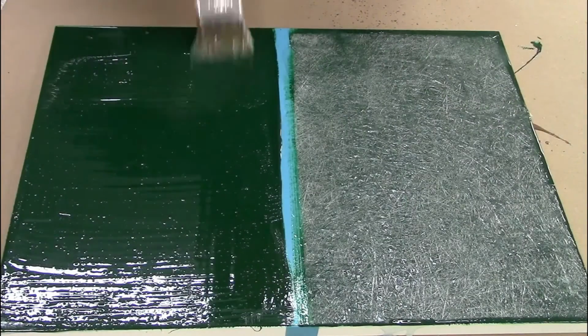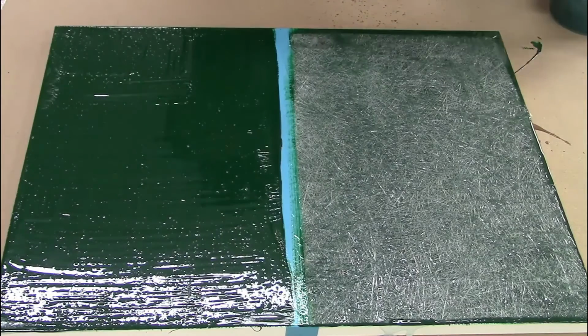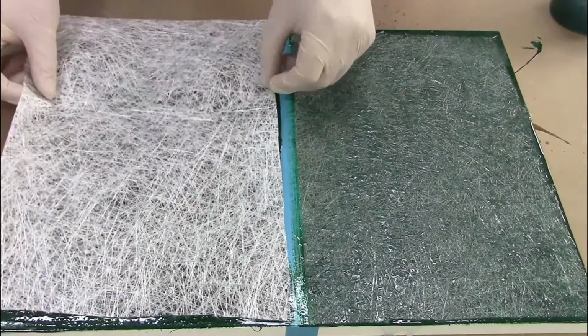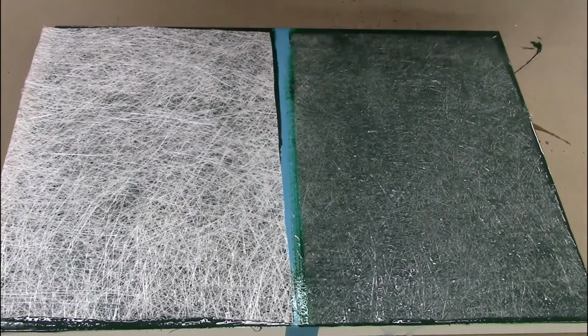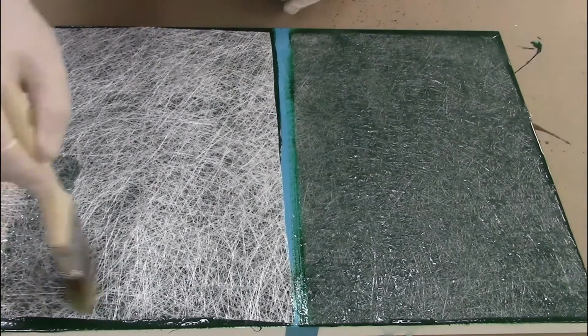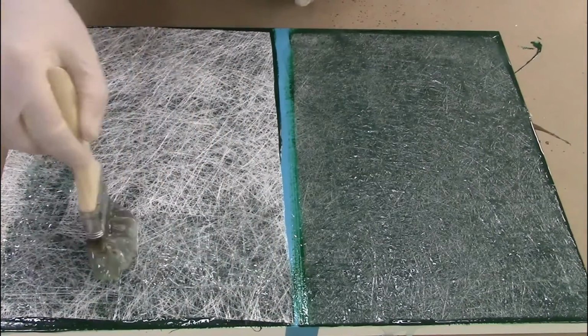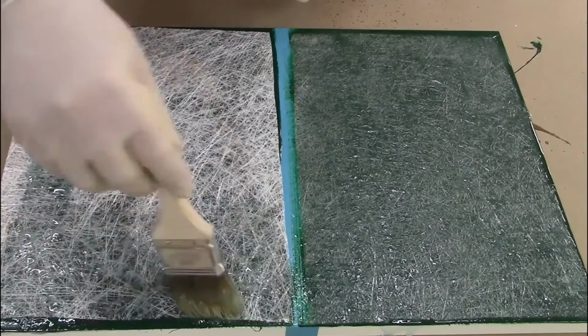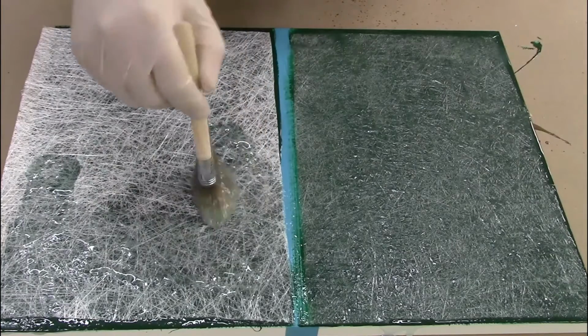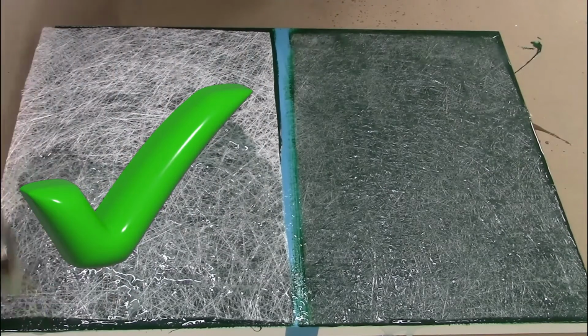Here, on the left-hand side of our sample panel, we're applying resin mixed at a 2% catalyst dosage and at a perfect working temperature of 18 degrees C. The product is also conditioned to the same working temperature, so it should cure within a reasonable timescale.